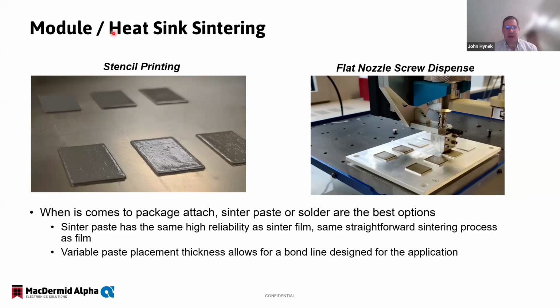Sinter paste has the same high reliability as sinter film, and the straightforward sintering process is the same. And the variable paste placement thicknesses allow for bond lines designed for the application. So you can control those bond lines really well, and you can control the geometry of that print or dispense really, really well with the paste product. So not all is lost.